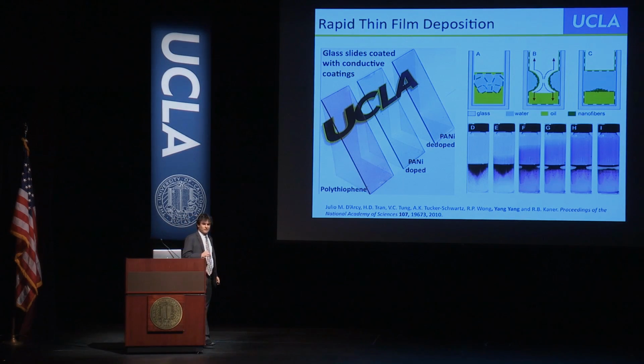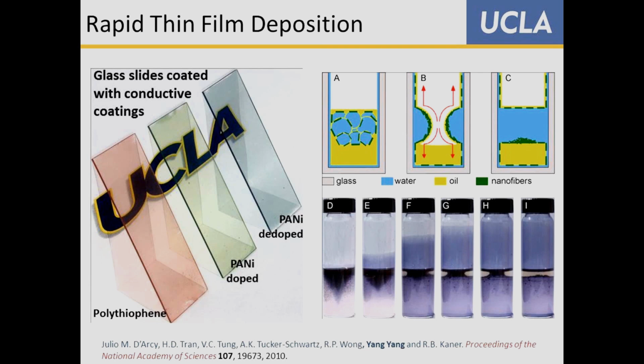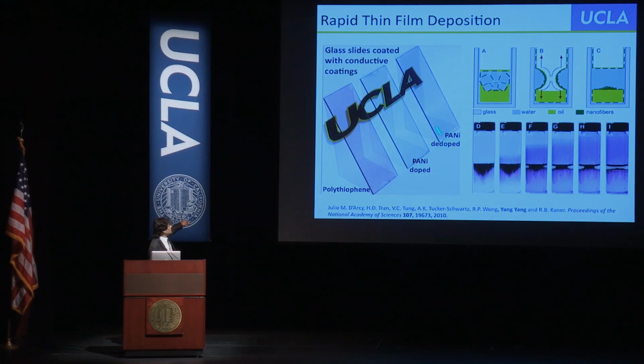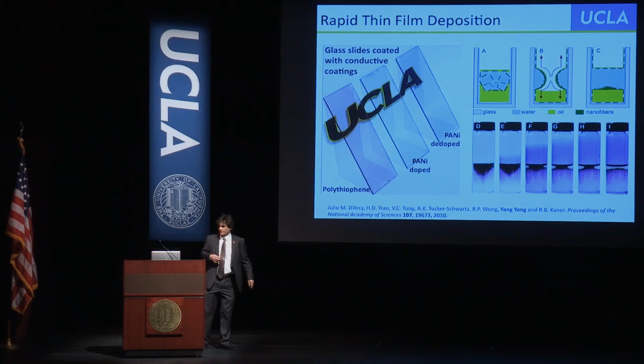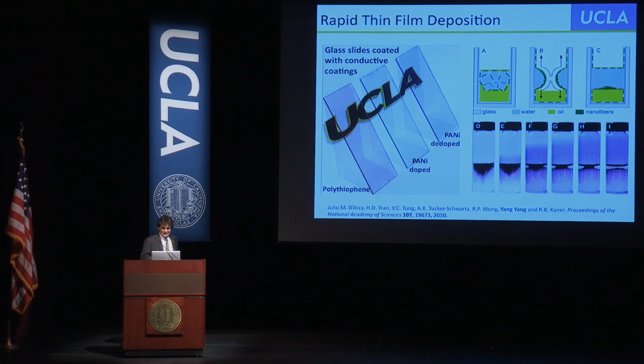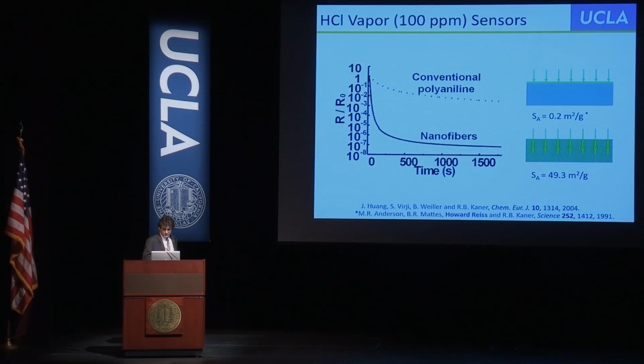Now, we've also looked at coating technologies, and one of my students, Julio Darcy, invented a coating material that, if you think of making salad dressing, you take oil and vinegar or oil and water and put it together and shake it. Of course, it tries to separate, and it forms a catenoid. And so what we did is we took our nanofibers of the conducting polymer, we put it in that oil-water mixture, and as the catenoid breaks up, it sends a film growing up the side, the wall of a tube. And if you put a glass slide in, you can make all different colors. So here's polythiophene in red, and doped polyaniline in green, and de-doped polyaniline blue. So we can make coating technologies. In fact, he earned the silver medal in the National Collegiate Inventor Hall of Fame competition for this discovery.